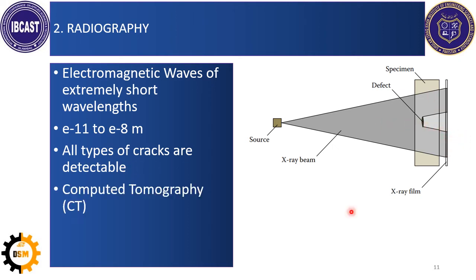And the new way of doing it is the CT, the computed tomography. CT scan gives you 3D radiographic images, and it can detect in-surface and deep inside cracks as well. But as X-rays are dangerous for health, they are hazardous, so this is not recommended for structures which are near the human interface. And also you need very good safety precautions and trained people to operate these systems.